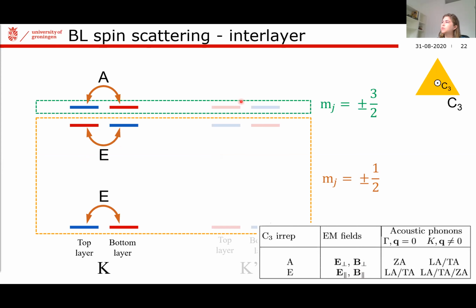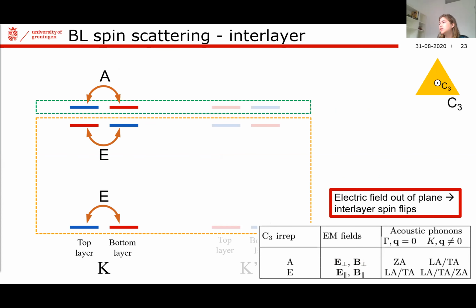And for the states transforming as mj equals plus and minus 3/2, since time reversal doesn't play a role anymore, now this flipping is actually allowed, and it's allowed with operators that transform as the A irreducible representation. And those are electric and magnetic fields out of the plane of the monolayer. So that actually means that for these systems with optically created spins, like Marcos has shown that it's possible to achieve, we can actually tune the degree of spin flipping processes happening between the layers with an electric field in plane for these states and out of plane for these states.